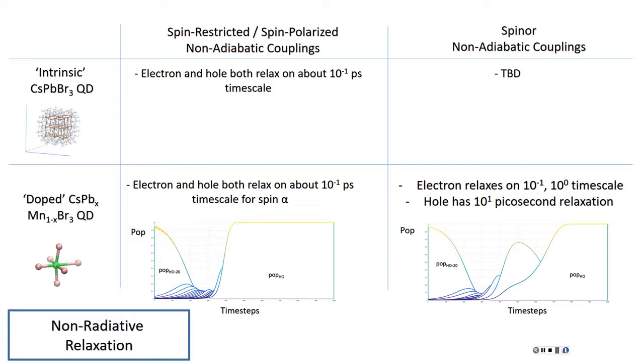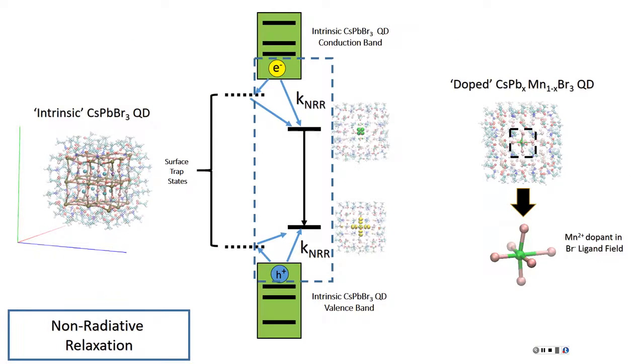So you can get spin flips for non-radiative relaxations? Yes. If you are in the basis of spinors, you're allowed to. Actually, it can be not really slow. This is the reason why you may want to track the magnetization as a function of time. If there are no spin flips, then overall magnetization will stay constant. But if you have spin flips, it may change. You will have a kind of distribution, spin up, spin down.